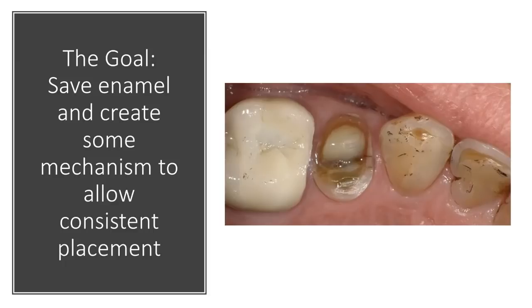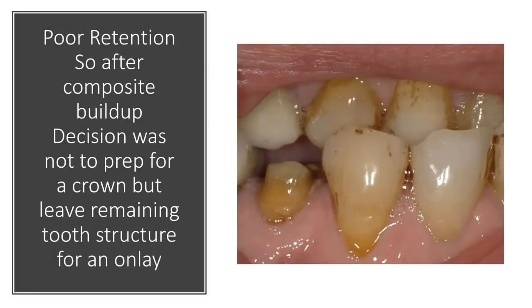So I did a self-adhesive technique where I self-adhese using a universal bond. In this case, it could be All-Bond or one of the many self-adhesives. No reason to etch there because it's only dentin. And you do a core buildup. And the core buildup is a small buccal cusp. This is all I've got.